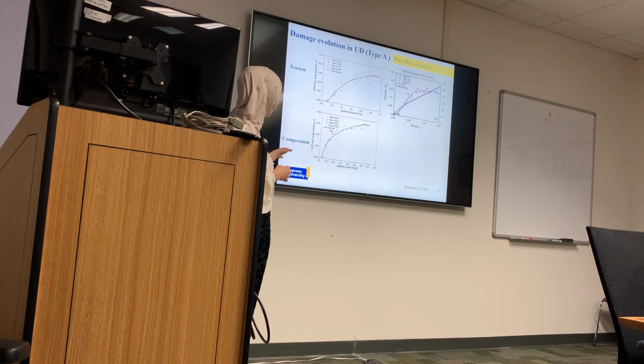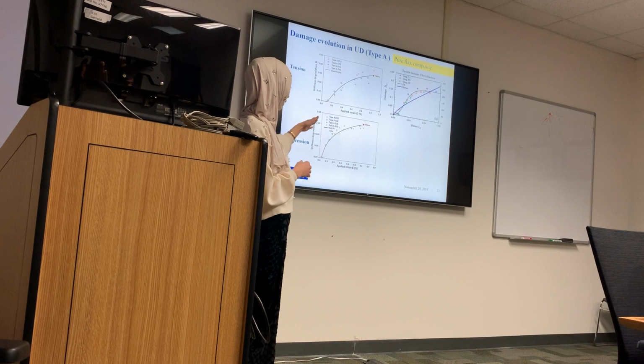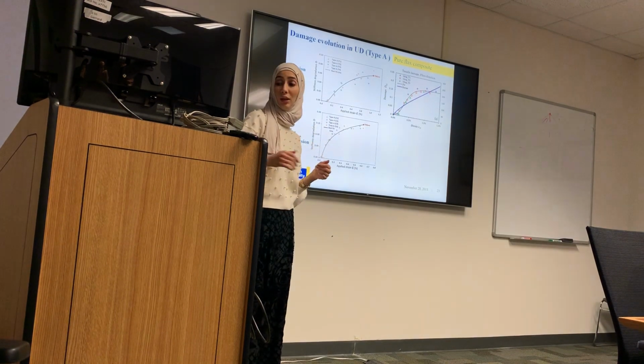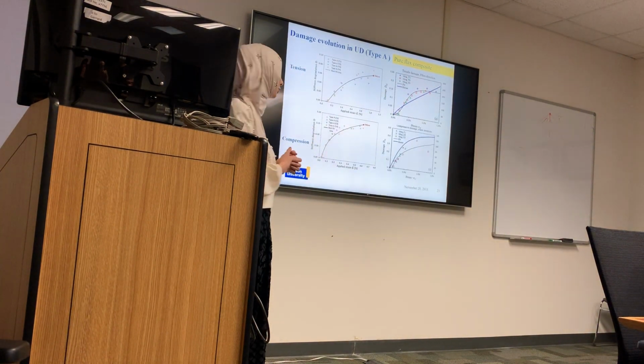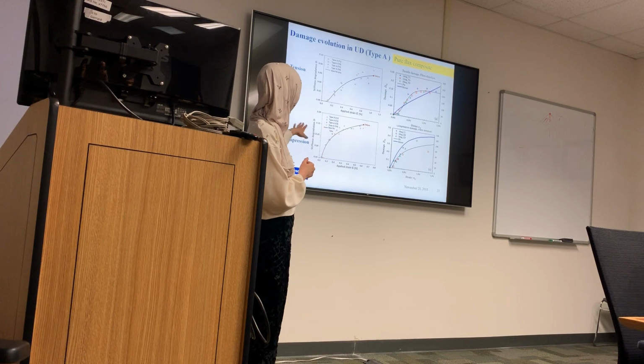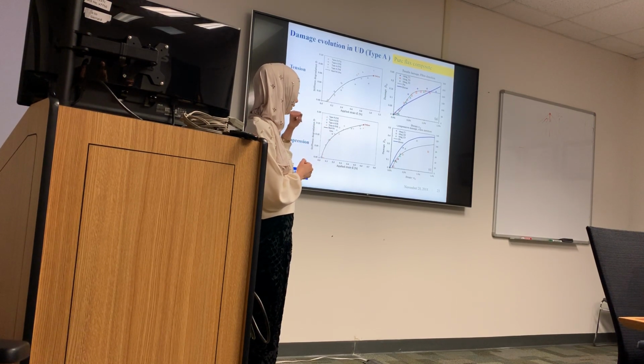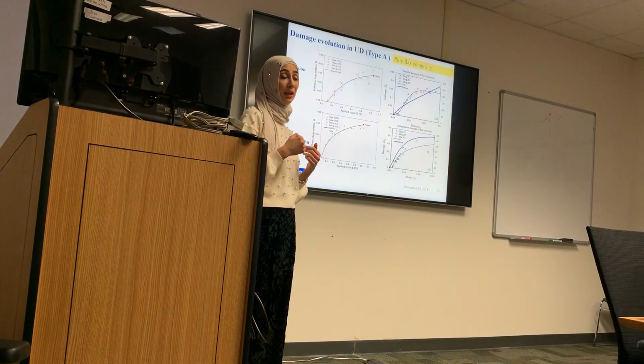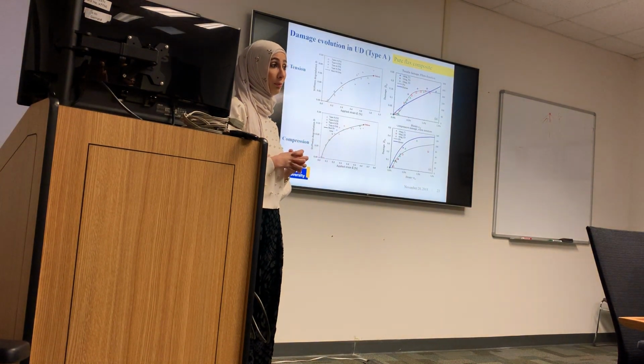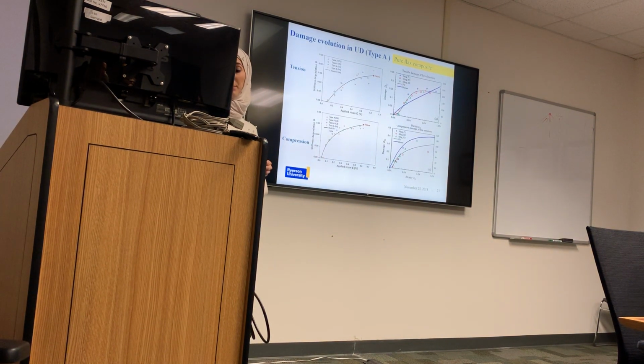You see under compression, it had a threshold, then it increased quite a bit, then it started to plateau. For pure flax, the one available in literature, you see obviously the damage was less compared to that one. This is attributed more to the reorientation of the microfibrils in the flax fiber.